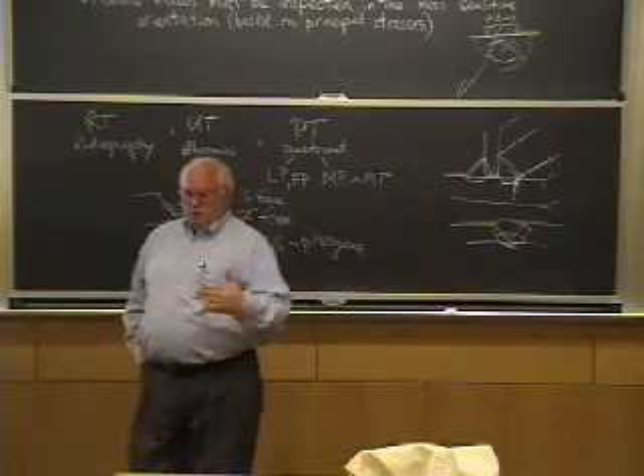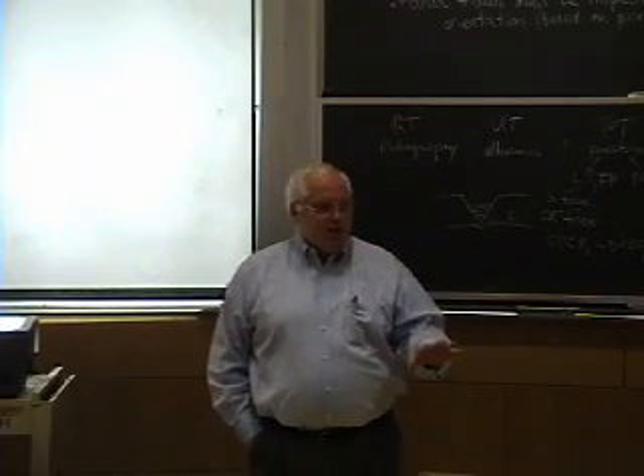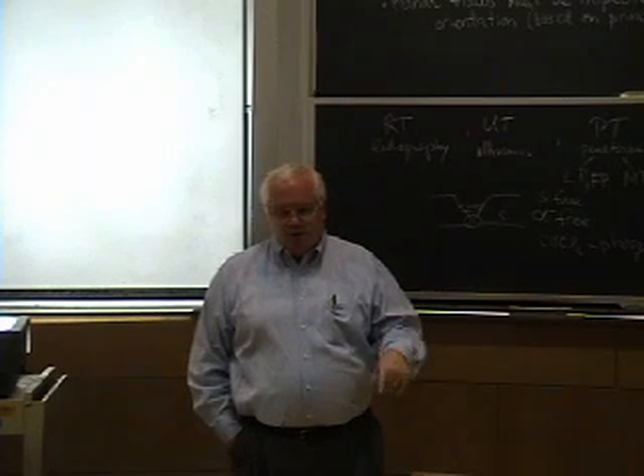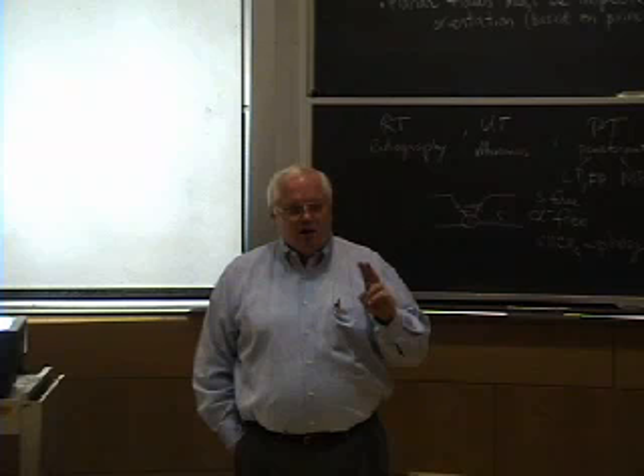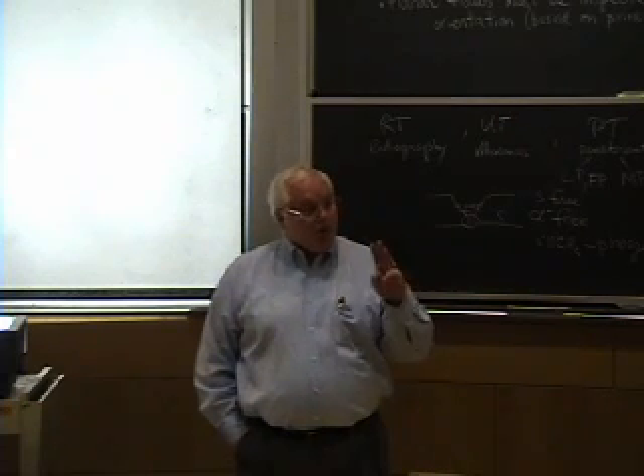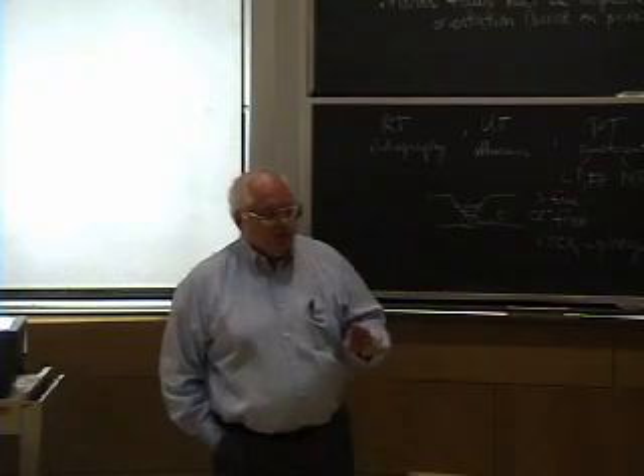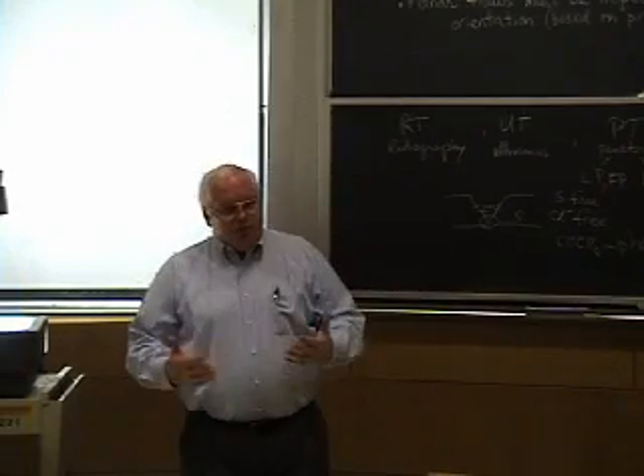I'm trying to go into three dimensions here. Right? So magnetic particle, we talked about different levels of inspection. For a bridge or a building, the simplest level, unless you specify something else according to the structural welding code, is you always have to do visual. Then they might, on a more critical weld, specify for steel buildings magnetic particle. Or for aluminum structures, they might specify penetrant testing. Penetrant testing basically is the same type of thing as magnetic particle. You just have to go in there with the spray cans to do the penetrant testing. But it's often fillet welds, and you're often looking for cracks at the toe of the weld.